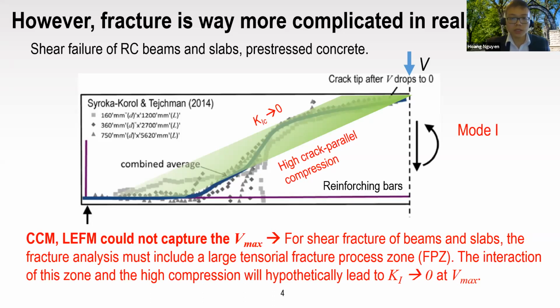So regarding the interactions of this zone, as you can see from the illustration here, it is similar to the strut-and-tie model people usually use in ACI. When subjected to a shear crack, there is a compressive line forming between the support and the applied loading point. And because of that high compression, there will be interactions between the compression that was just created and the opening mode caused by the applied load. So from that mismatch, we think there should be some interaction there, and that is why the LEFM and cohesive crack models could not capture the Vmax here.